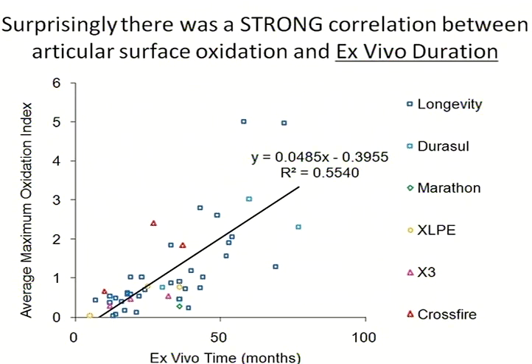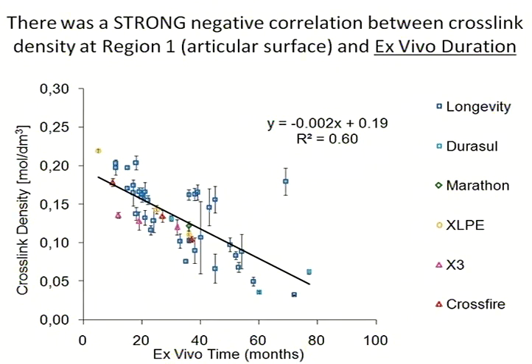And what did we find? We did find that these polyethylene cups were oxidized, which we thought would never happen. And furthermore, that there was a very strong correlation between storage ex vivo and increased oxidation. And exactly the same was the case for de-cross-linking. So that strong chemical bond that we thought was resistant to anything in the world was not resistant when it was out of the patient and stored in air for some time.